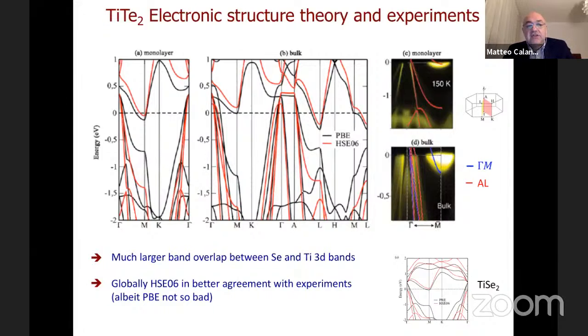The electronic structure is similar to the other case, but now the band overlap is more substantial and is very similar both in PBE and HSE06. However, as you can see, the velocity of the band is different in PBE and HSE06. This is true both in the monolayer and the bulk.